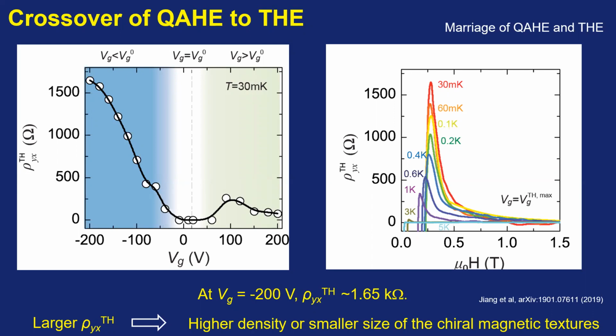So this is the magnetic field dependence of the topological Hall resistance in the sample as a function of the temperature. We can see this hump feature will disappear with the increase in the temperature. So at 5 Kelvin it is almost 0. We can see when the gate voltage is minus 200 volts at 30 millikelvin, the topological Hall resistance is about 1.65 kilohm. This is much higher than the previous systems for the topological Hall resistance. And this kind of large topological Hall resistance just indicates a higher density of this kind of ferromagnetic texture, or a small size of ferromagnetic texture in this sample.